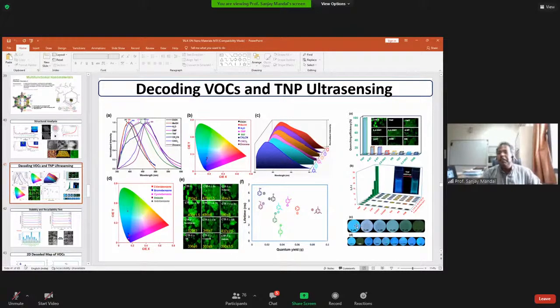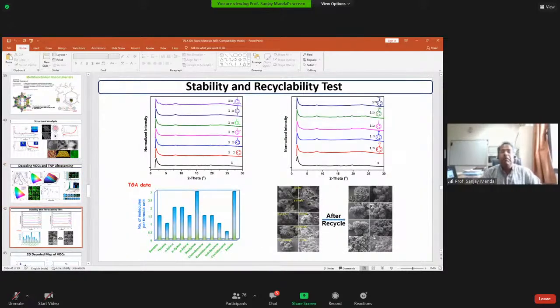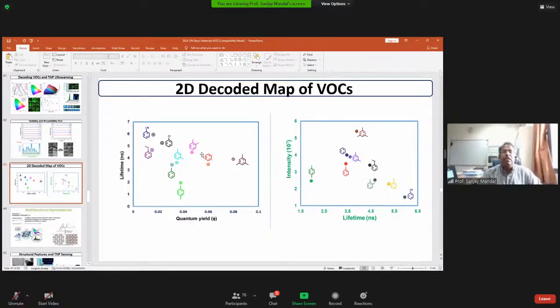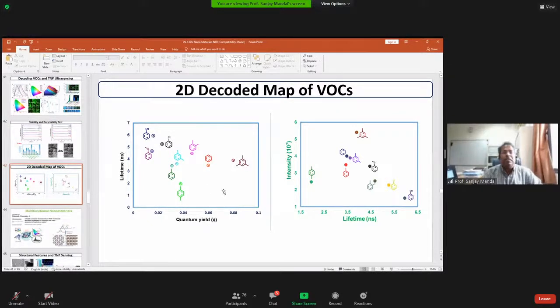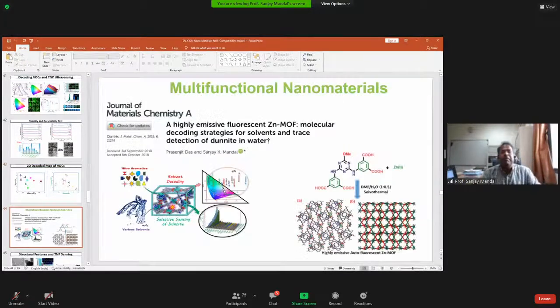And we did the filter paper test also to tell you what is the detection limit. And always you have to show the stability and recyclability. We have done through powder X-ray diffraction, and we also have looked at TGA of different solvents. And here again, we can tell you the VOCs by quantum yield versus lifetime versus intensity. If you have unknown stuff, we can tell you it is mesitylene based on this map.